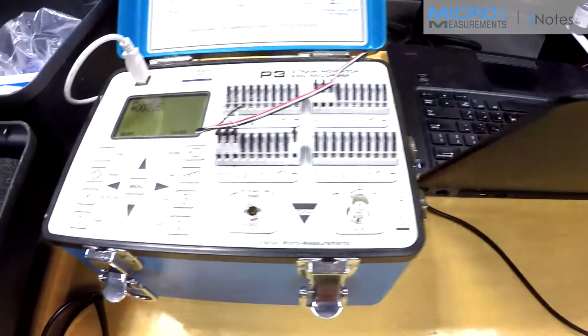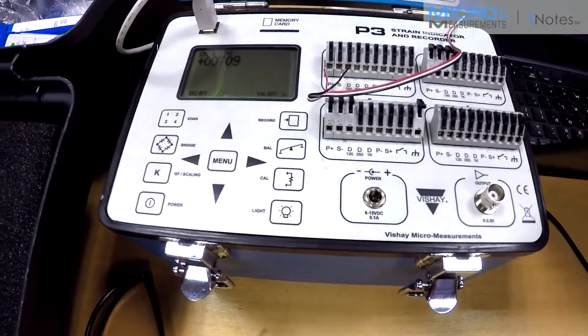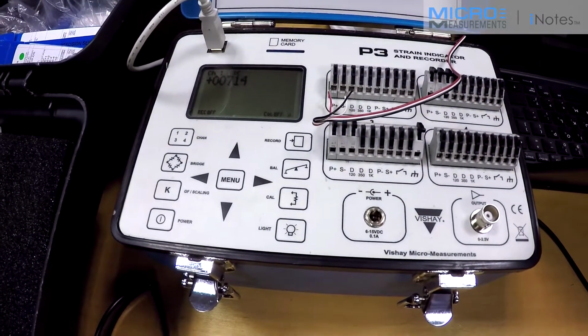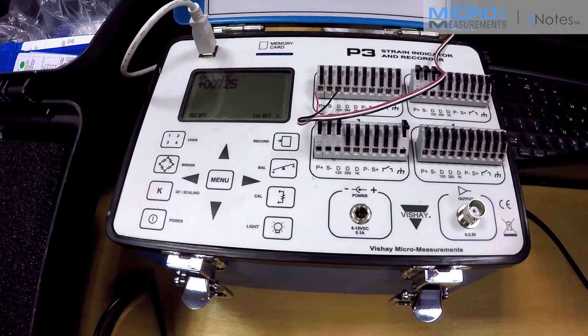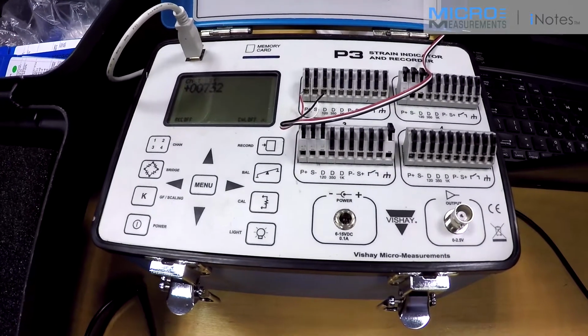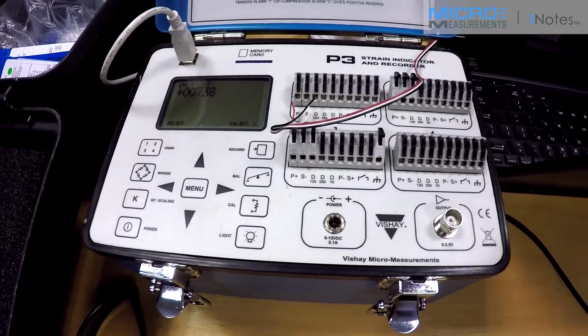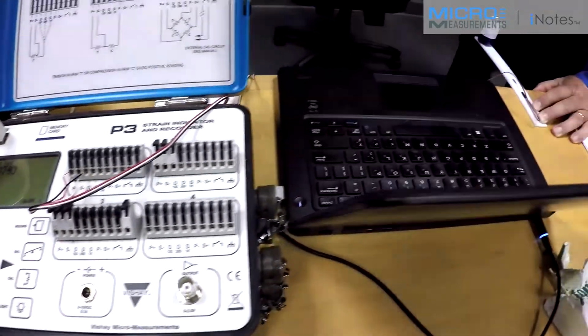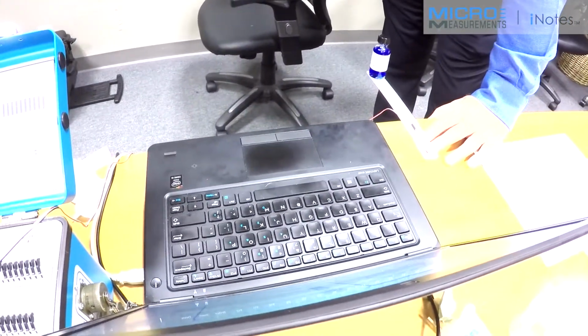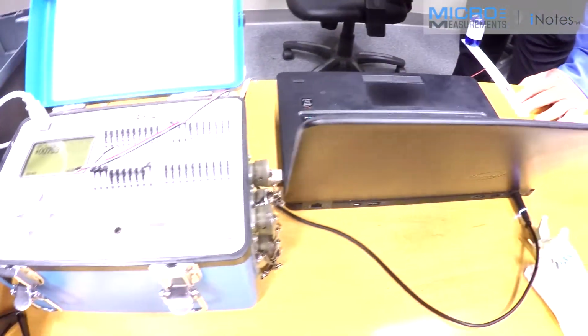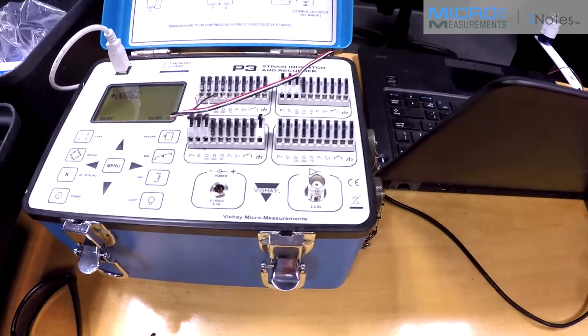So now to further illustrate this plus creep, put a little static load on it and look at the output over time. And you can see that that output is increasing with time under a static load, again indicating that we're seeing plus creep in the plastic. The strain gauge is not lying to us. It's telling us the truth of what's actually taking place in the substrate material.